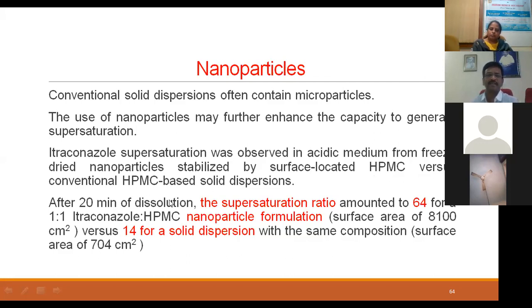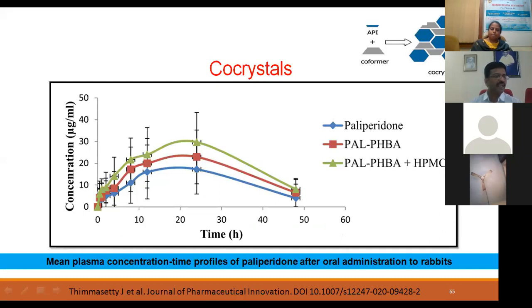And it is compared with the solid dispersion that was prepared from only HPMC. Yes, there is a difference. After 20 minutes of dissolution, the supersaturation ratio amounted to 64 from the nanoparticles, and the value was 14 with the solid dispersion. So there is an enormous increase in the supersaturation ratio with the nanoparticles for itraconazole. So we studied all this.